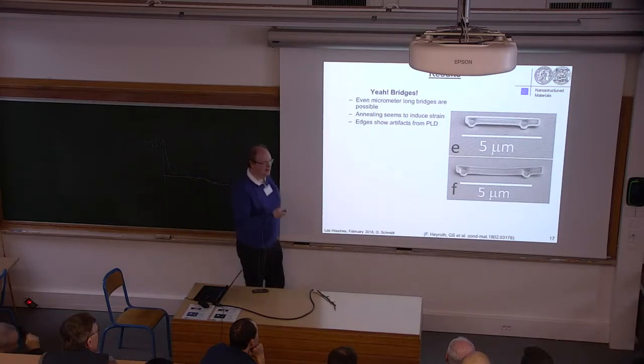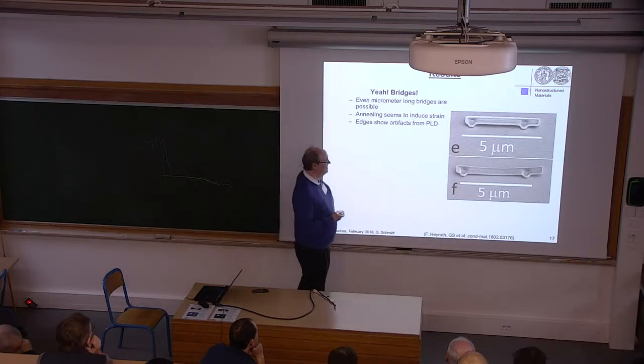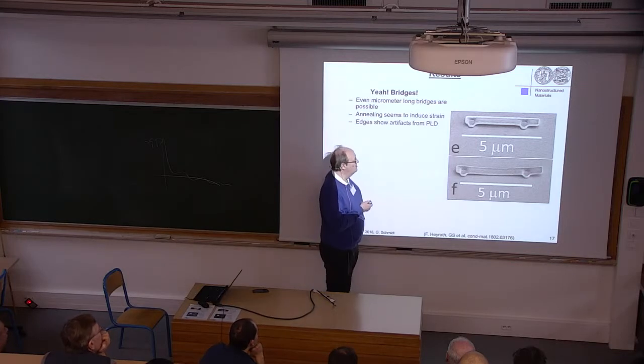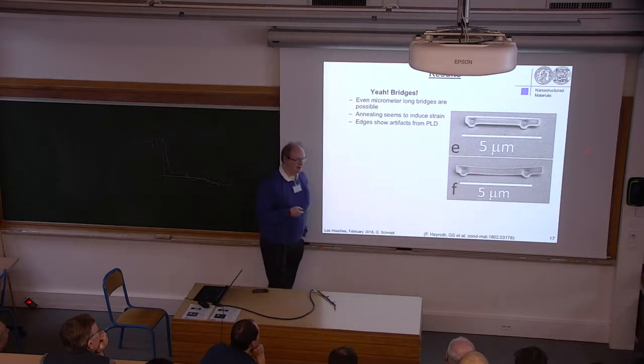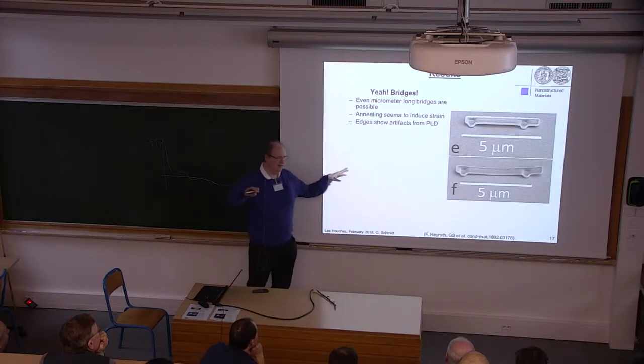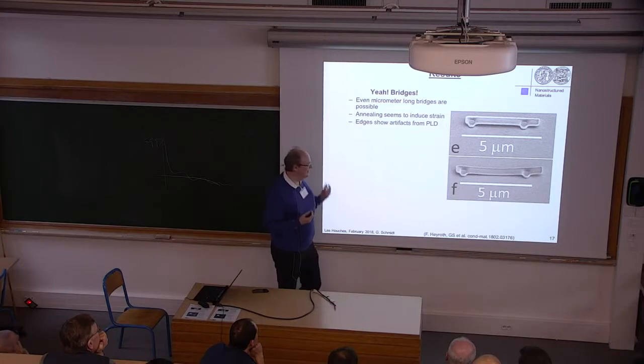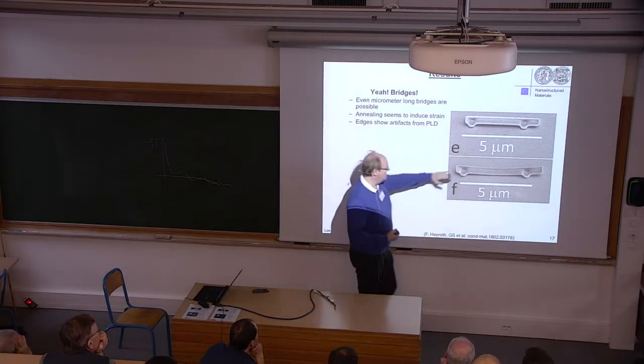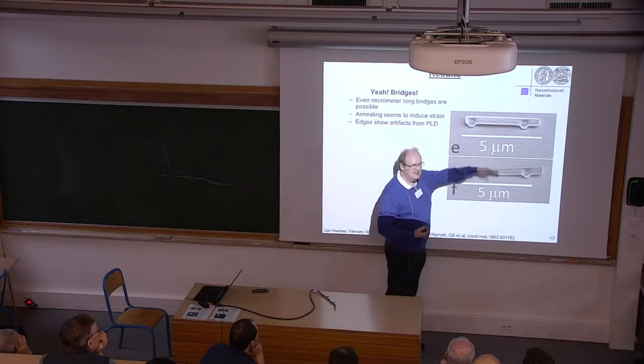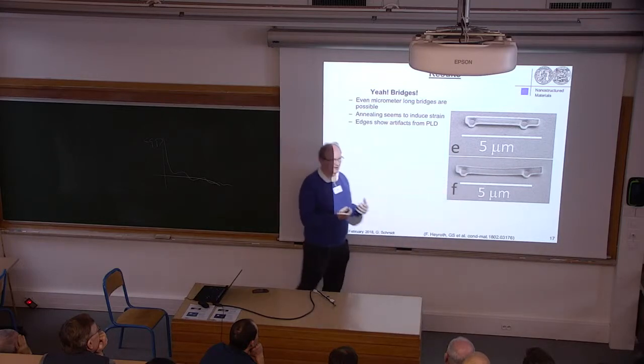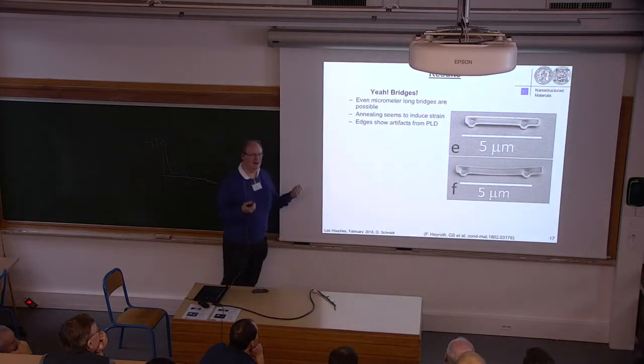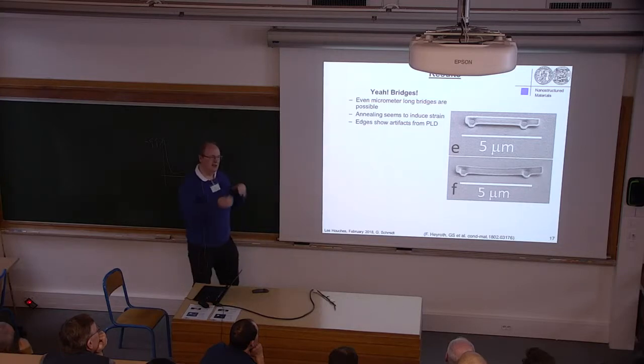So this is what we get. These were more or less the first results that we had. The top one is before the annealing step, and the bottom one is after the annealing step. It looks as if the bridge is bent, but it's not. The picture is misleading. It's actually these sidewalls which look as if the whole structure is bent. In the TEM pictures, you will see that the center of the bridge is completely straight.